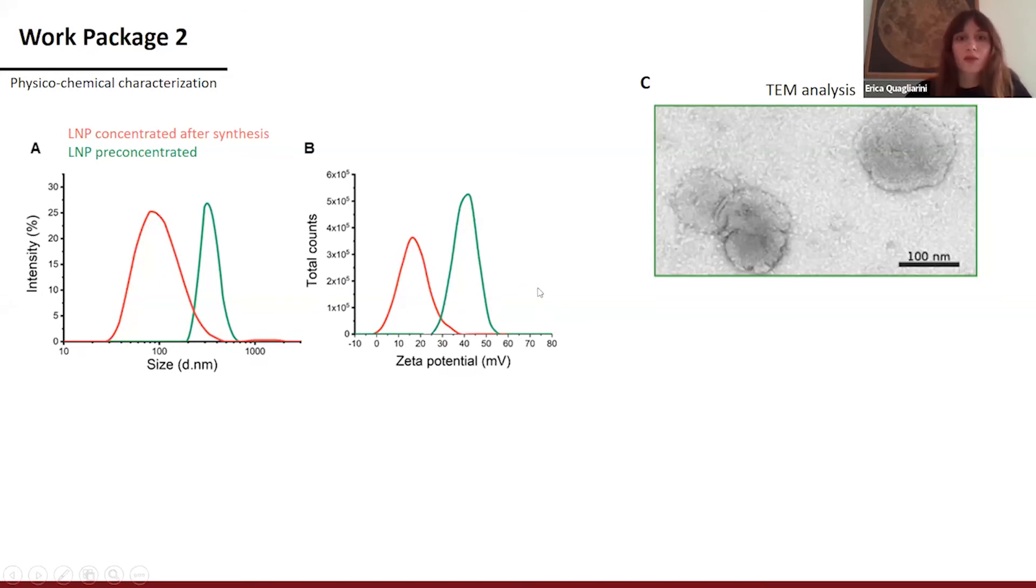Next, we performed a transmission electron microscopy analysis on the PEGylated lipid nanoparticles. The ultrastructural analysis showed round-shaped vesicles, and confirms the size obtained with dynamic light scattering measurement that was about 100 nanometers.